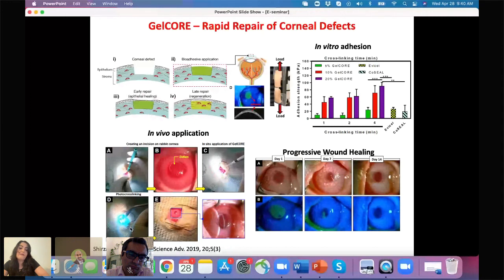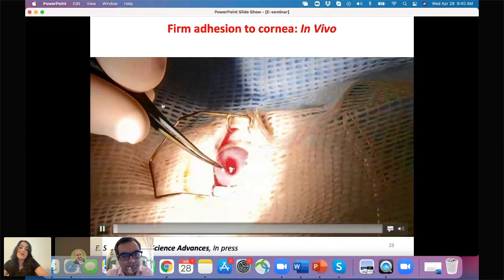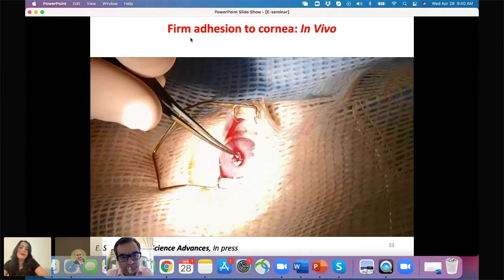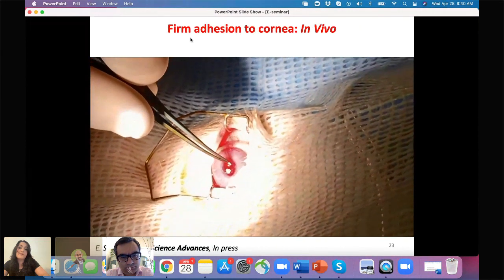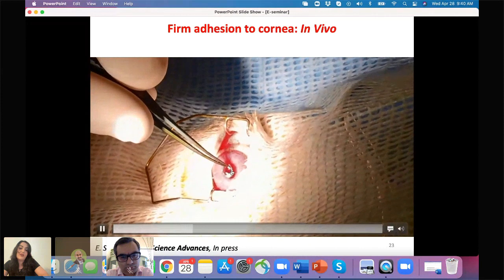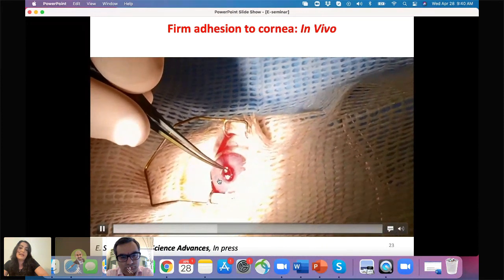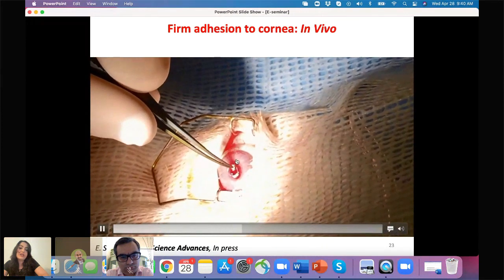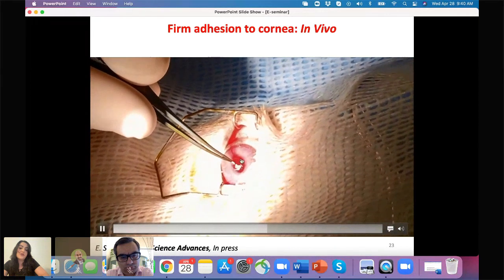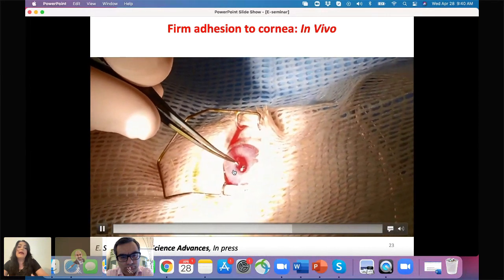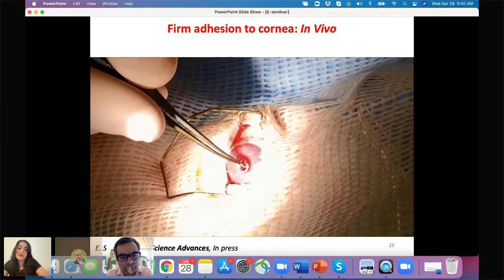And here is the defect that we sealed with our bioadhesive material. And then we observe progressive wound healing over time once we apply these biomaterials on the surface of the cornea. So here is the video from our in vivo test showing that the adhesive material is cross-linking on the cornea, and then we show the firm adhesion to the cornea tissue. So the hydrogel can remain on the cornea and help with the regeneration and repair over time.